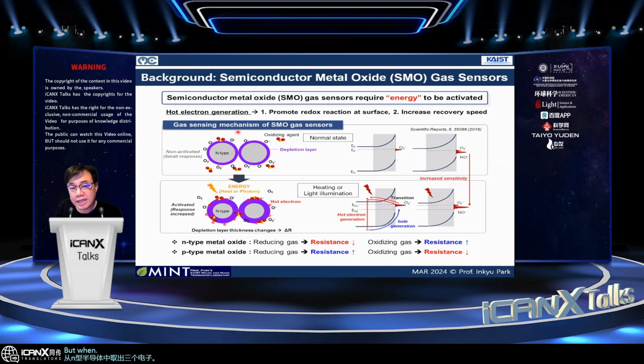But when the reducing gases such as hydrogen or ammonia come, the hydrogen or ammonia react with the surface adhered negatively charged oxygen ion. Then this will be detached by forming the water vapor, and then it will return the free electron back to the N-type semiconductor. By doing so, it reduces the depletion layer and also reduces the energy barrier for the electron flow. So in the reducing gas environment, it will have lower electrical resistance.